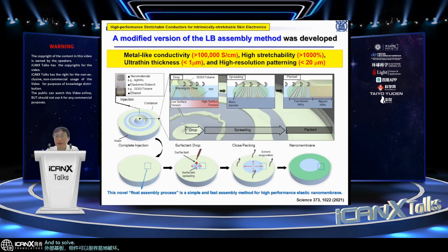And to solve that issue, we developed a modified version of the Langmuir-Blodgett assembly. Not just using nanomaterials, but also we added toluene, an organic solvent, and also SEBS solution.